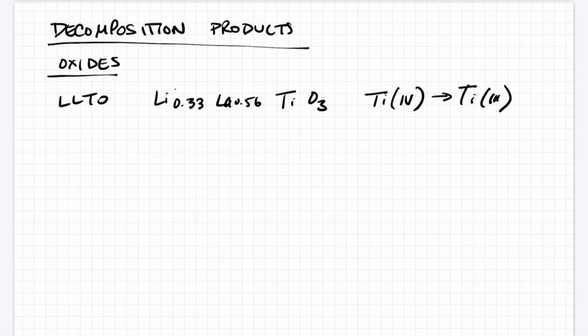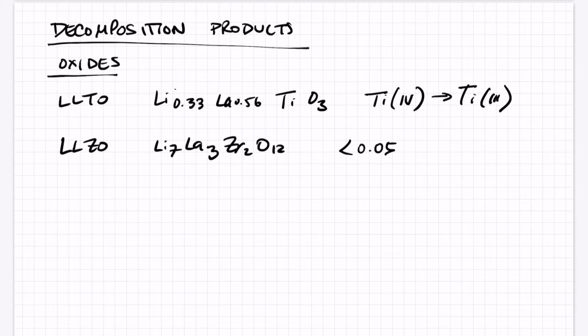Well, and then there's also LLZO, the garnet that we talked about. Right. So here, LLZO has been, as we've discussed, quite attractive as a solid electrolyte because it can be stabilized against lithium metal, mostly. I mean, the stability window for LLZO goes all the way down to almost 0 volts versus lithium plus. It's more like 0.05, so you can get pretty close.